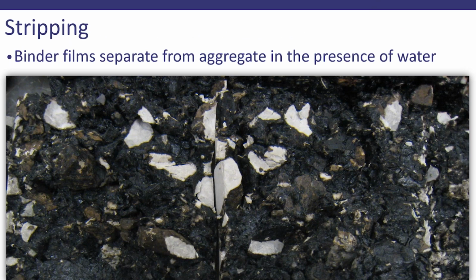Okay, and then a distress that's usually pretty hard to see or truly identify without coring the pavement is called stripping. And this a lot of times will show up from the surface and look kind of like rutting, but it's where the binder films within the mix are separating from the aggregate. You know, asphalt is rocks and the oil coats the rocks and sticks them together. But when the oil comes loose from the rock, then we're going to see some, the lighter color is really just broken rock, but you can see a lot of places where it's brown. That is where the binder films have actually separated from the aggregate surfaces.